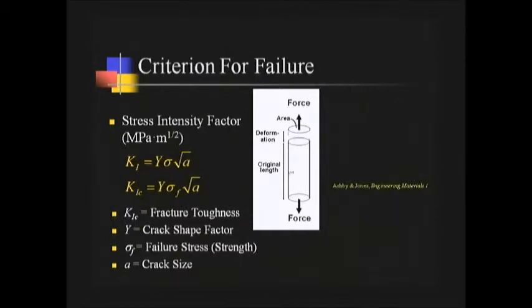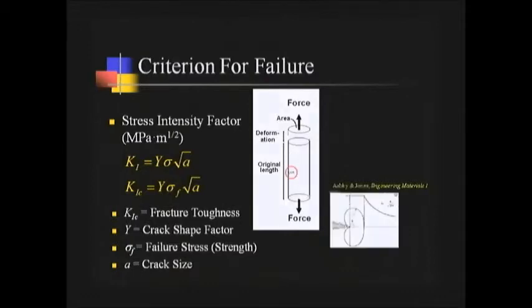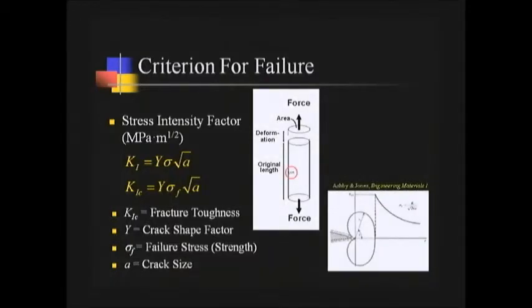Okay? And so we have a piece of material here, and we are pulling on it with some force, and that force will induce a stress all over the material. In this simple case we have drawn here, the stress can be calculated by dividing the force by the cross-sectional area. Force divided by area is stress. However, the material is covered with lots of flaws, cracks, pores all over the surface. And if we look closely at that, we can see that the stress near the flaw in the surface is concentrated by the presence of the flaw. So in the material near the tip of the flaw, we have a concentrated stress, and that's what I'm talking about when I say stress intensity factor.